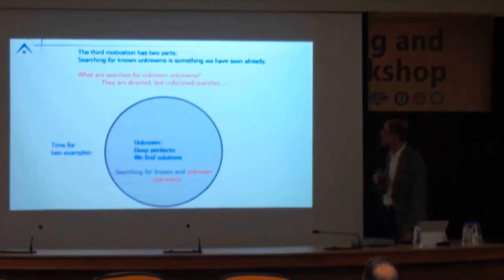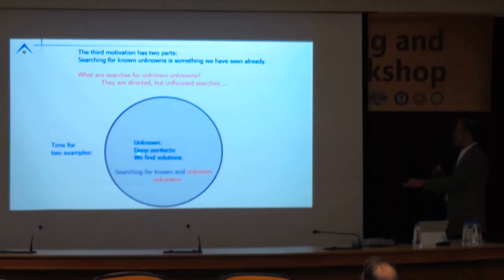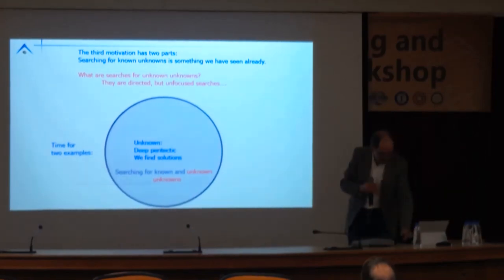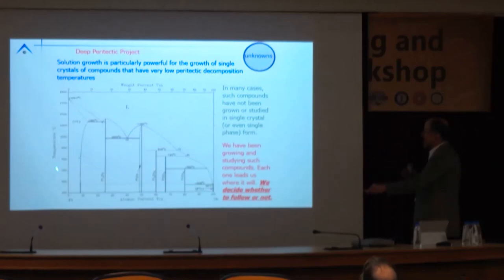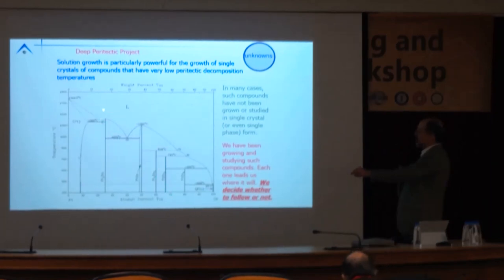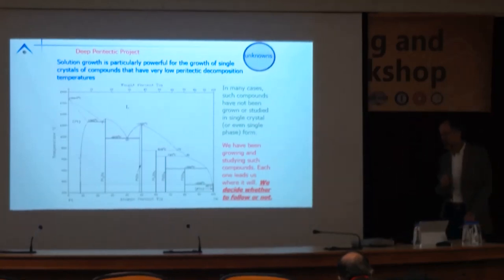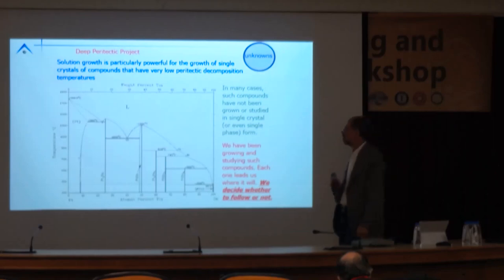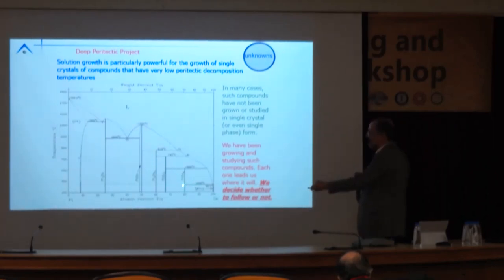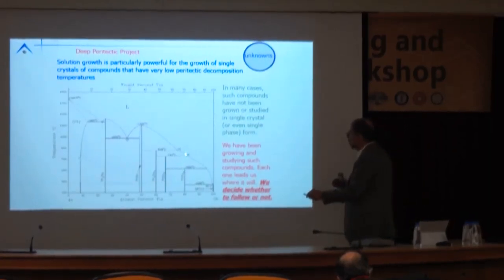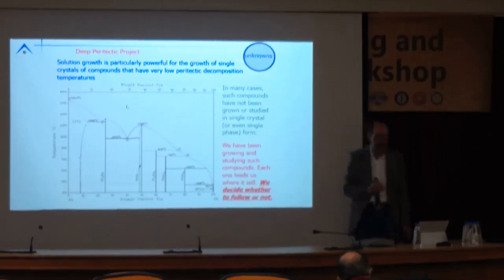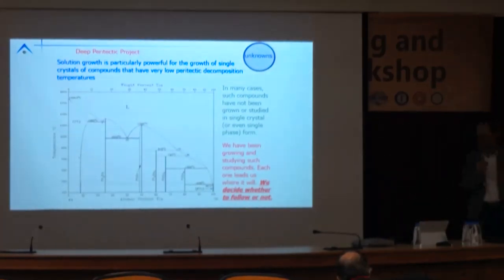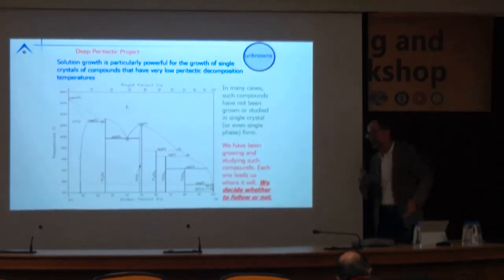So let me give you two examples of what's happened. One's called the Peritectic Project, the other's called Web of Solutions. Okay, the peritectic project. So, a binary phase diagram: temperature, composition, here's platinum, here's tin. You have two types of compounds. You have congruently melting compounds that are generally relatively easy to form. You can take a solution of that composition, slowly cool it, and get a crystal of that composition. And then you have incongruently melting compounds, or compounds that decompose peritectically. But this decomposition temperature is well below the liquidus of the same composition, which usually indicates that it would be difficult to grow single crystals of these by conventional arc melting or Bridgman or other techniques.